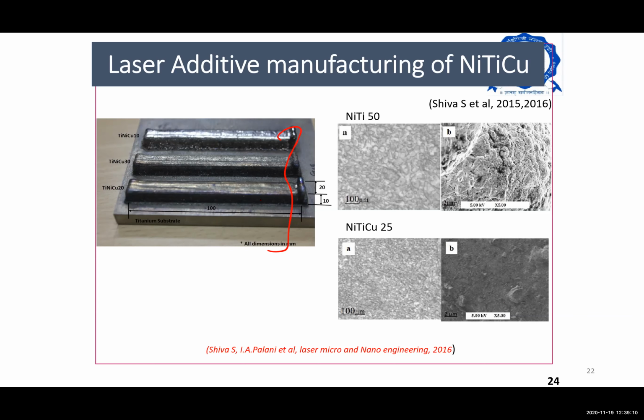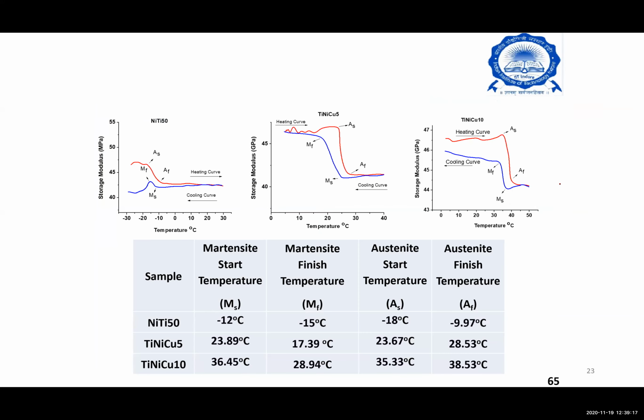And we also did a complete detailed characterization, including scanning electron microscopy and a DMA analysis, basically in order to study the storage modulus capability in detail. With respect to the storage modulus capability, we could study the austenite phase and the martensite phase, and the mechanical correlation with respect to the austenite phase and the martensite phase behavior. And the most interesting thing is, this was highly helpful for us to map with our system and directly use it in the production field. Okay.